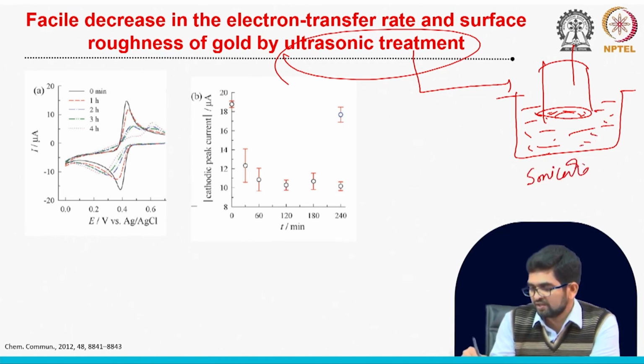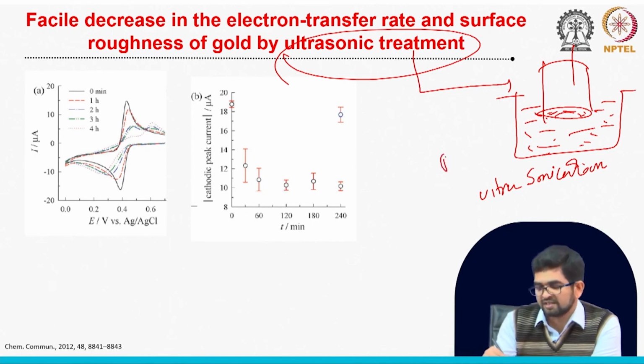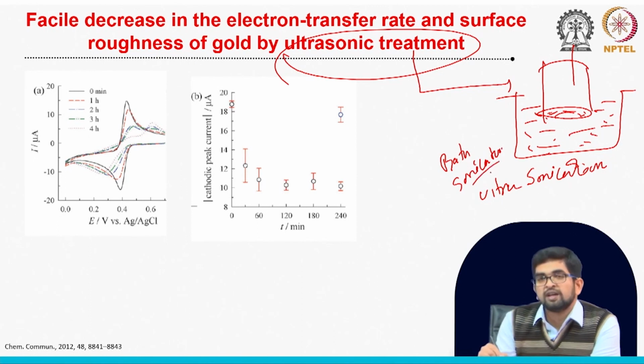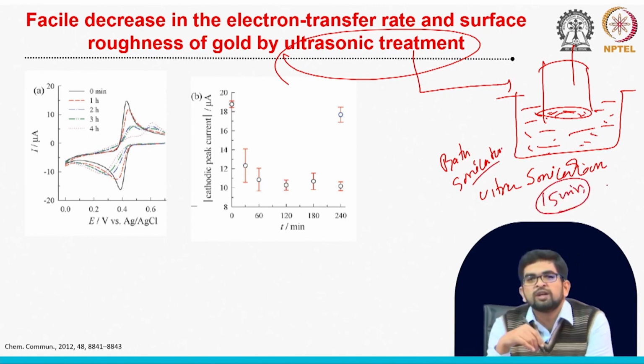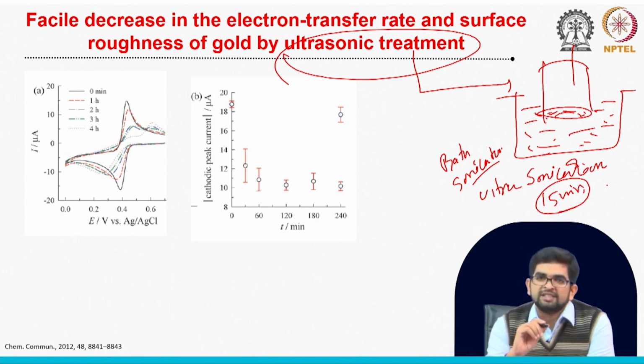Ultrasonication. We are sonicating this surface in a bath sonicator, for 15 minutes. But sometimes you may go for quite longer sonications. That effect I am now going to tell you. If you go for a quite longer sonication, it may impact your gold electrocatalytic activity.